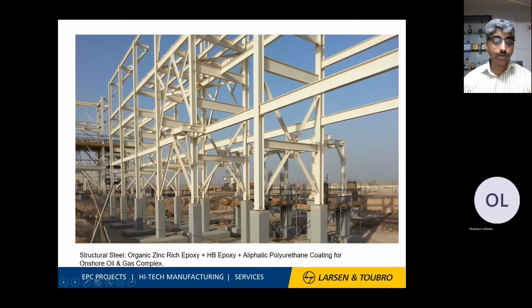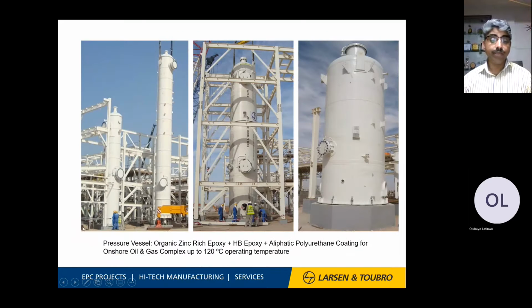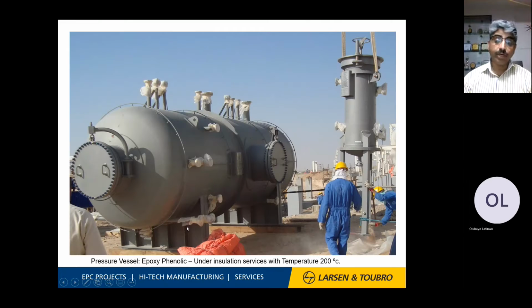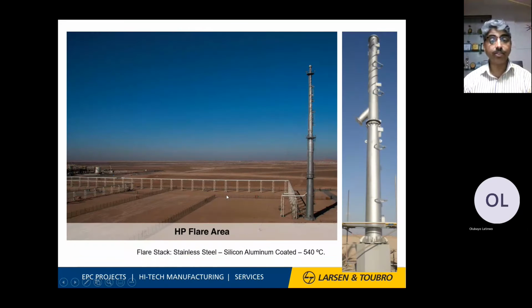Similarly, a structure in a normal environment, where you can apply zinc silicate followed by high build epoxy, then aliphatic polyurethane coating for any oil and gas structures. If you have pressure vessels for 120 degrees centigrade temperature range, you can use zinc silicate or zinc rich epoxy primer, high build epoxy, aliphatic polyurethane for the color. Similarly, under insulation, say for 200-degree temperature, you can apply this. Cleats are indications that there is an insulation over this particular vessel. So you can apply epoxy phenolic coats, which are high temperature resistant.